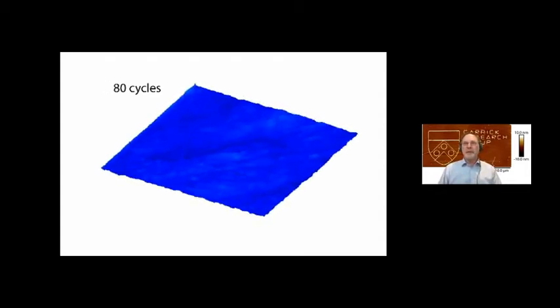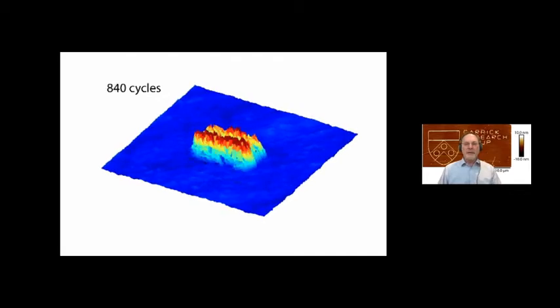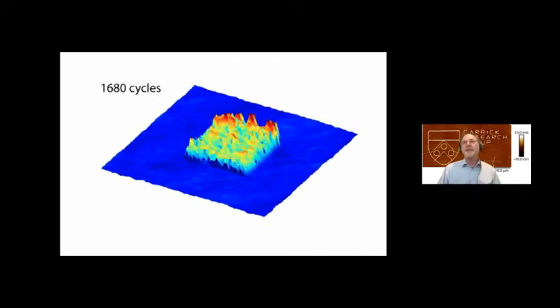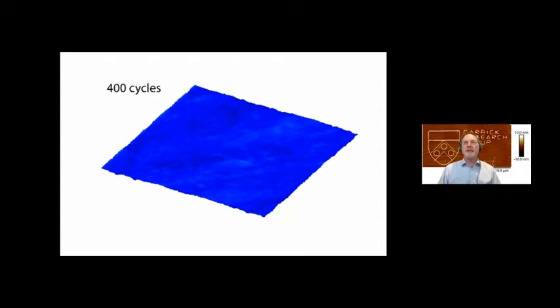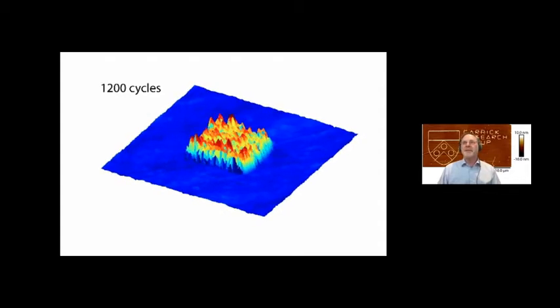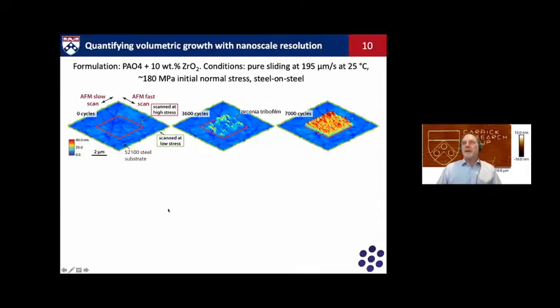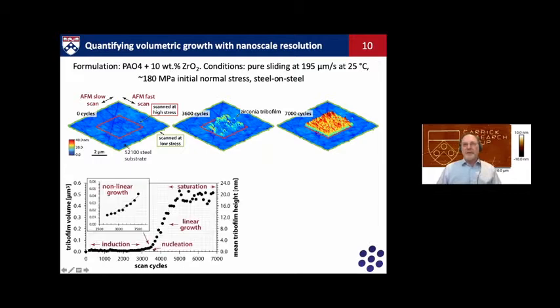It is strongly bound to the surface. We are not able to scratch the whole film off of the surface. It's quite tenaciously bound at its base. So the film grows. We see sort of an induction period, then sort of rapid growth, and then saturation at a height. In this case, this is only 20 nanometers. It can grow thicker if we use different conditions.